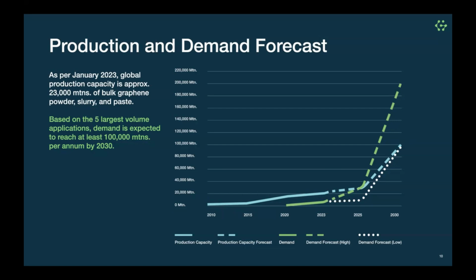And the other factor to keep in mind is that you're often using an extremely small amount of it. In the case of concrete, for example, which is tremendously price sensitive, you might be using 0.03% by weight. So this is tens of grams per metric ton of concrete where you're using graphene. And so when you're using such a small amount of it, even if the graphene itself on a per unit basis seems to be an expensive material, in fact, when in use, it's quite economical.